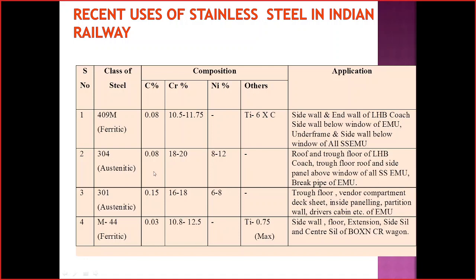The composition of both is more or less the same, only the nickel percentage is a little bit changed, and chromium and carbon percentage also changed. In 304 carbon is very less, 0.08 percent only, whereas 301 carbon is 0.15 percent, a little bit increased. Chromium is more or less same, 18 to 20 or 16 to 18. Nickel percentage also varies, 8 to 12 percent, here 6 to 8 only. So less nickel and more carbon in 301, and less carbon and more nickel in 304.